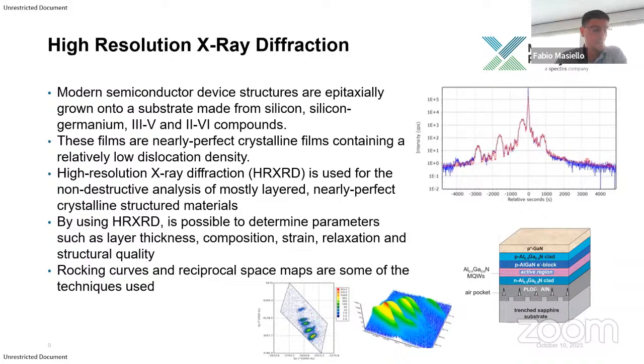epitaxially grown structures, so multi-layers, as indicated here. These films are very close to nearly perfect crystalline films, and they typically have a low dislocation density. That's why you need such a higher resolution. And what you do practically, again, non-destructively, is analyze these layers in nearly perfect crystalline structure material. The parameters that you are looking for in this case are layer thickness, composition, whether the layer has strain or is relaxed, and the structural quality.